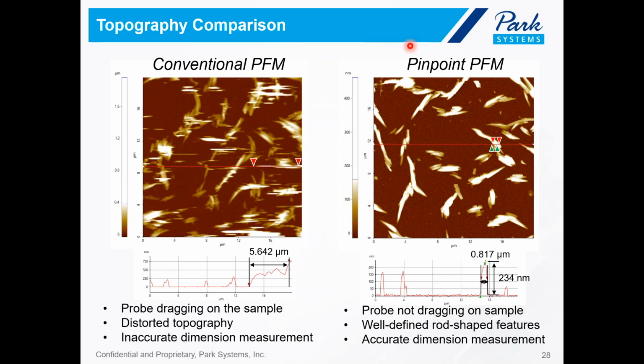On the other hand, under the PinPoint imaging conditions, the annealed phenanthrene polymer was well distinguished from the underlying substrate, and dimension measurement can be made easily. For instance, here we have a rod that's 0.817 micron in width and about 234 nanometers in height, as you can see here. The reason we have better results with PinPoint PFM is that the probe was retracted far away from the surface to a safe height at every pixel prior to approaching the surface again. The scratching between the probe and the underlying substrate was then effectively eliminated, leading to significantly improved imaging quality.